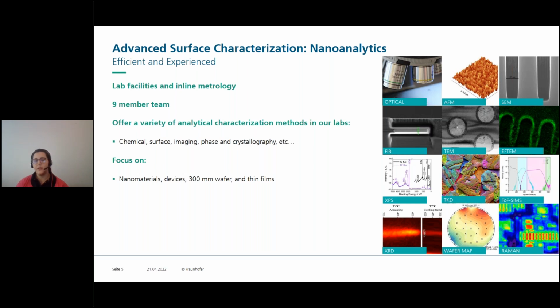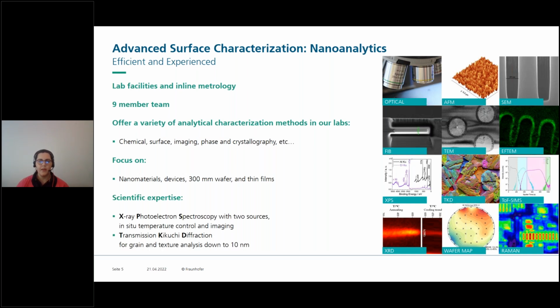TKD is transmission Kikuchi diffraction, which is a relatively new technique, and it helps with texture analysis. TOF-SIMS, time of flight secondary ion mass spectrometry, helps with elemental composition. X-ray diffraction is for crystallography. Wafer mapping, for example on your 300 millimeter wafer, helps understand thickness uniformity, and Raman spectroscopy helps understand the chemical composition, the structural fingerprint of your samples. We do have detailed scientific expertise in both X-ray photoelectron spectroscopy and transmission Kikuchi diffraction.